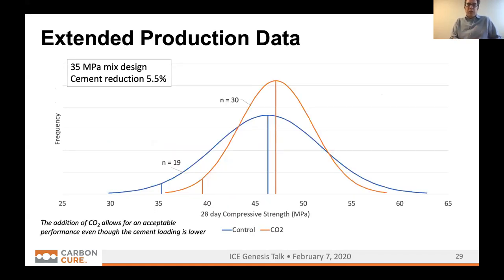That example was just a one-off with a couple of loads compared, but if we look at greater data sets, we can see that this strength production validates this idea that you can improve the compressive strength. So this is a producer who has been sending out a 35 MPa mix design, and where they made a cement reduction of 5.5%. And you can see there's no difference in the 28-day strength of the control in blue and the CO2 in orange.